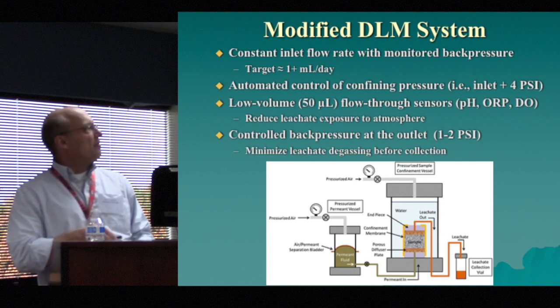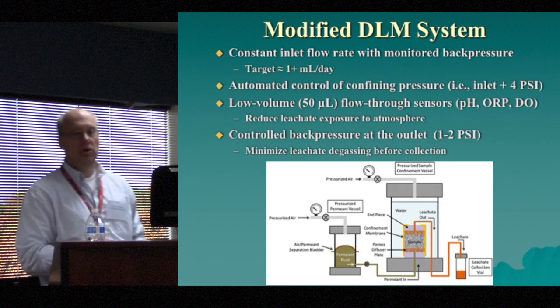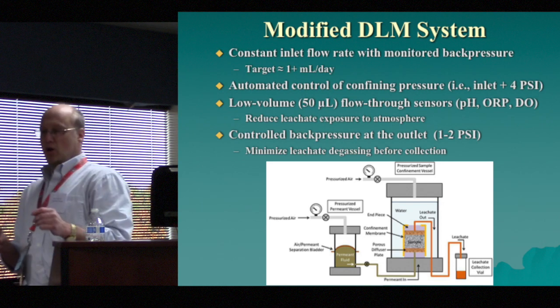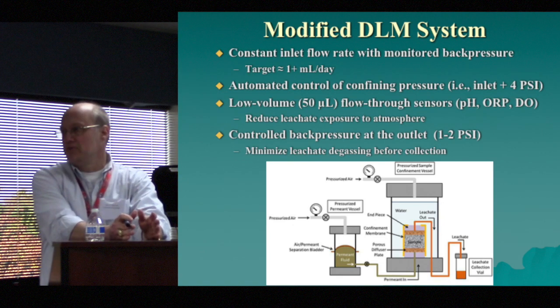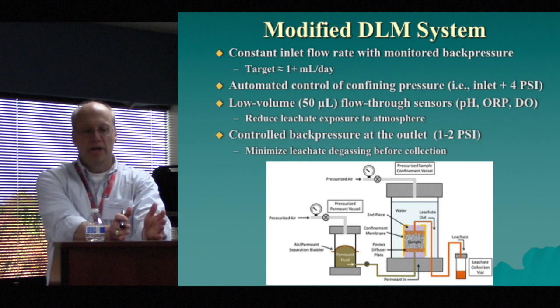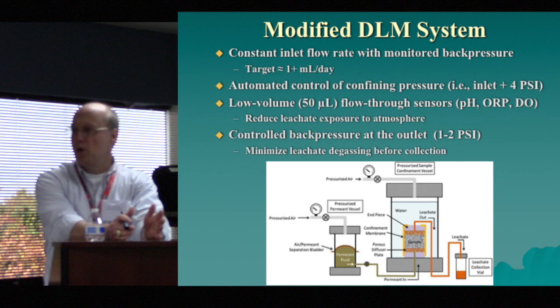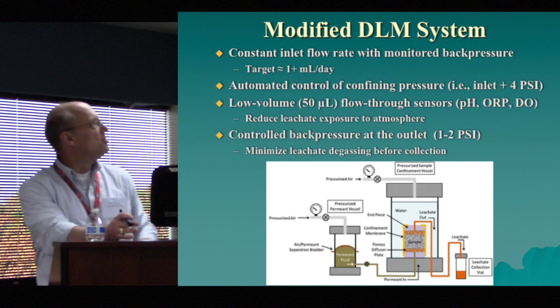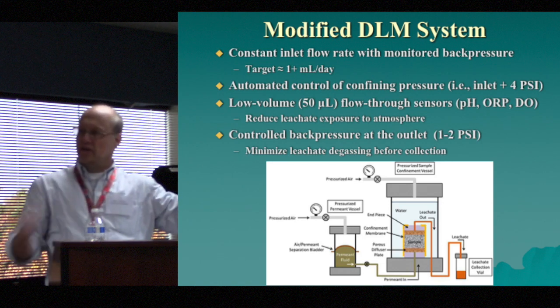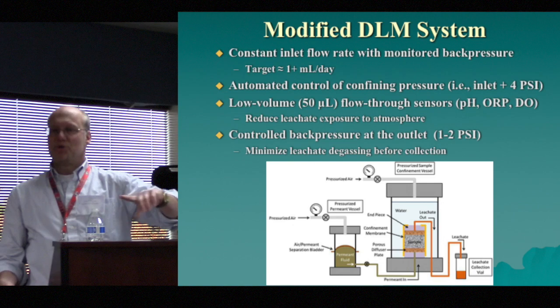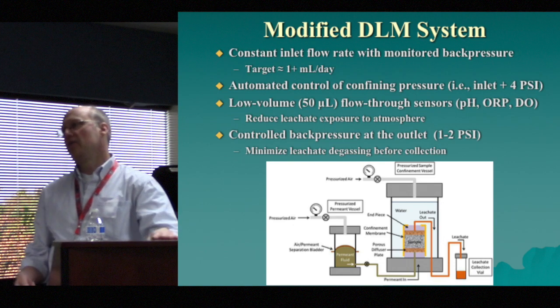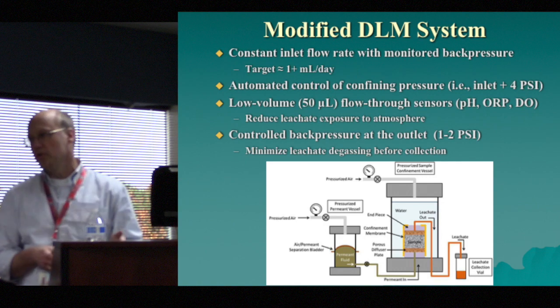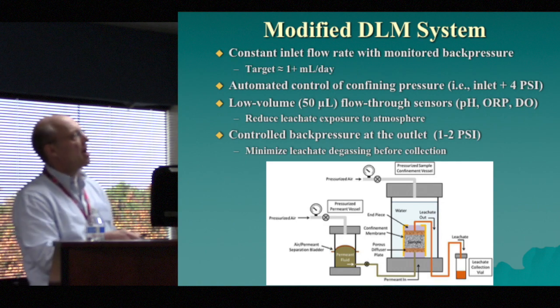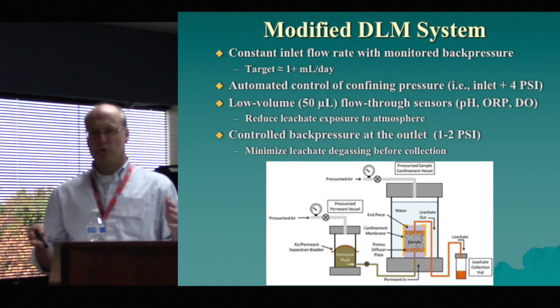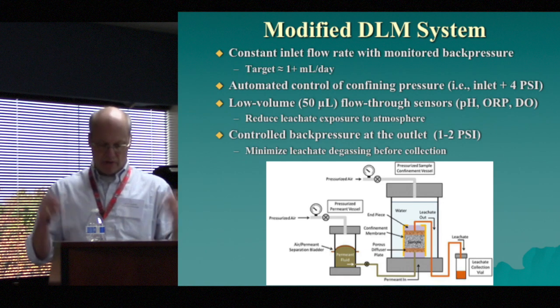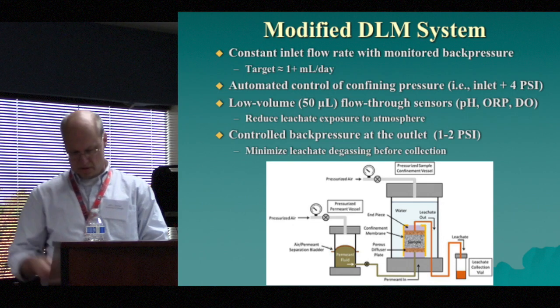Then the other final solution is there's actually a way to control the back pressure using essentially a piston system that allows the effluent to build up, pushing out a piston at a set pressure, so that you don't have 20 psi on the inlet and 0 psi on the outlet, which can cause problems because the sample can degas. And that can cause a problem with trying to measure anything with a flow-through electrode. And so that solves that problem, and it minimizes any kind of exposure of the sample to gases or loss of gases during testing. Next slide.